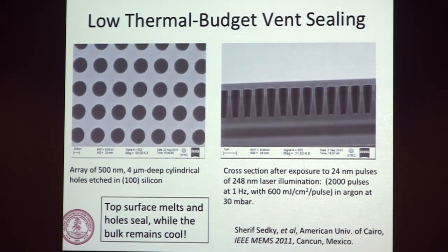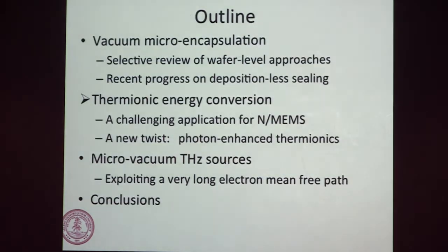So a long-standing collaborator, Sherif Sedky, was on sabbatical at Berkeley in 2002 and 3, and he's visited me at Stanford. He's a professor at American University in Cairo. We have an IEEE MEMS 2011 paper where the same process is done with a local laser annealing. So he has a pulse laser that heats just the surface, and his student emailed me last month, trying to model this. This is more like melting, but at the bottom it's cool. So it's the ultimate rapid thermal kind of annealing, and we can seal up the surface and keep the substrate cool. So in fact, to apply this for packaging could be very interesting. I keep forgetting this type of 24 nanosecond pulses, 2,000 pulses at 1 hertz, significant energy flux, and you're able to actually transform the surface of silicon. So this is a process done in his laser, which he's worked on for a number of years.